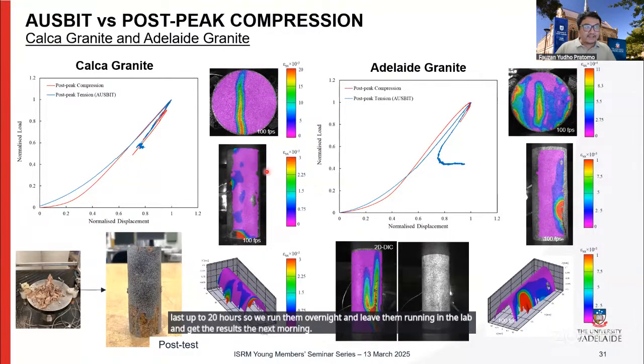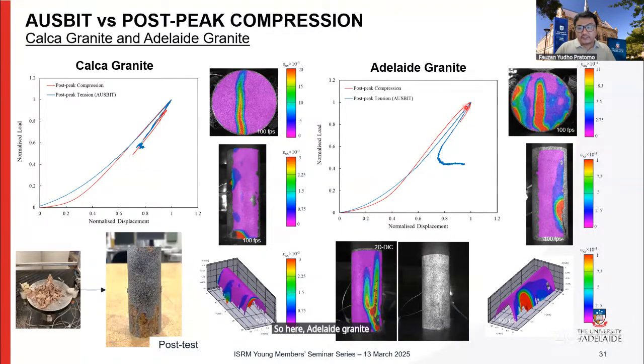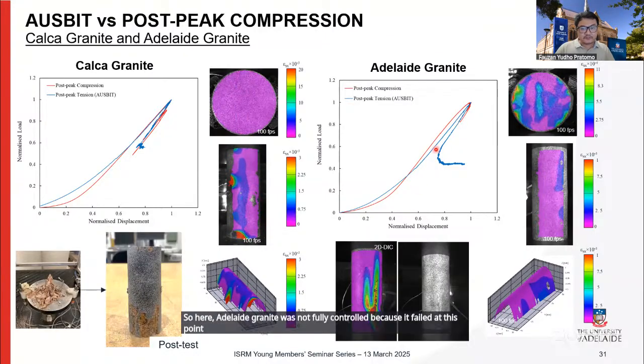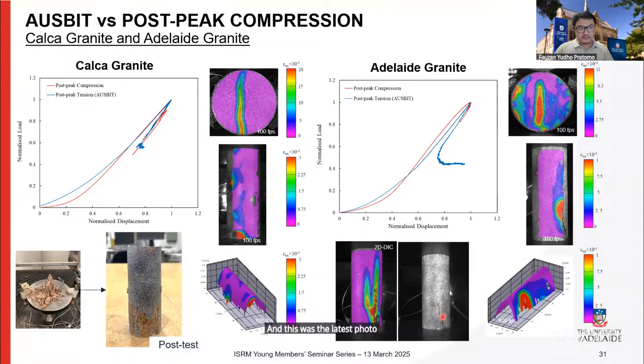So here the Adelaide granite was not fully controlled because it failed at this point, but still the snapback was acquired. And this was the latest photo based on the DIC before it fractured. A large axial crack formed, which was also captured by the 2D DIC.